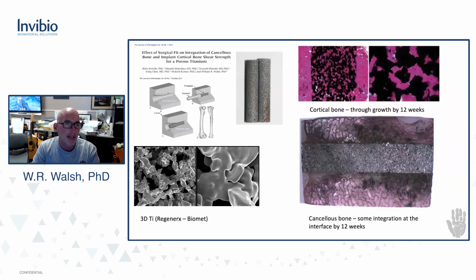I jumped 10 years, and we've worked with different groups. This was a three-dimensional titanium implant that was done with traditional manufacturing. From what I understand, very expensive, but you can make a 3D porous titanium implant with traditional manufacturing. And what you see with these implants is that in a cortical site, on the top here, bone grows right through the cortical site. But on a cancellous site, the bone really doesn't want to grow through even a porous material.